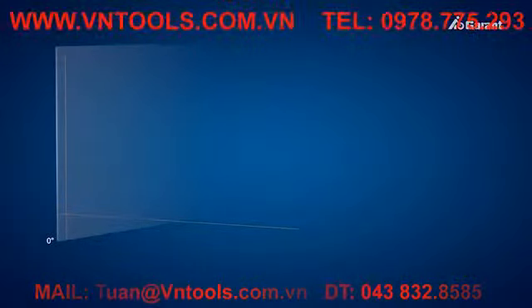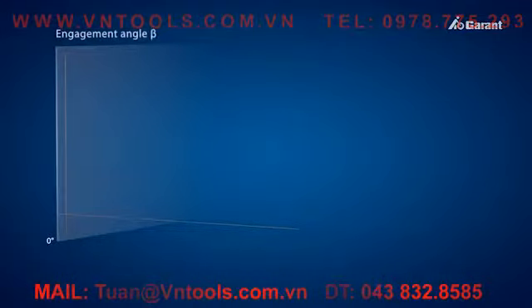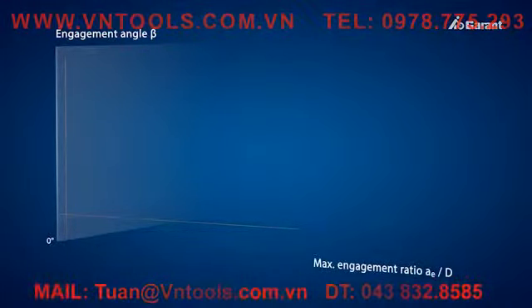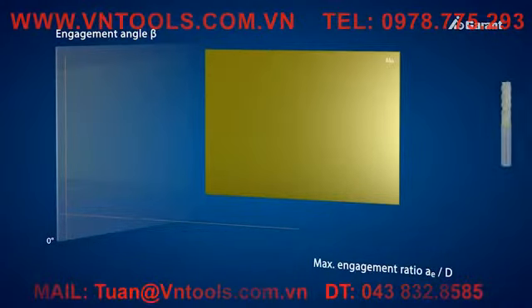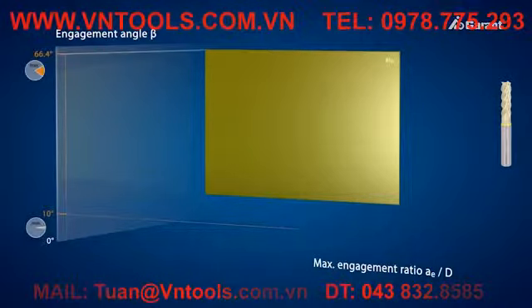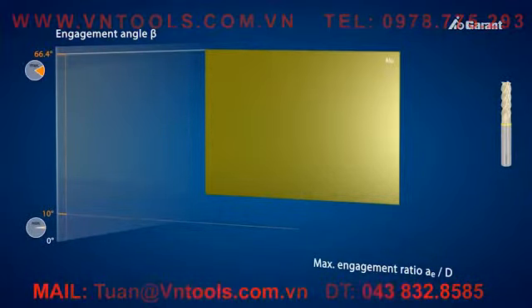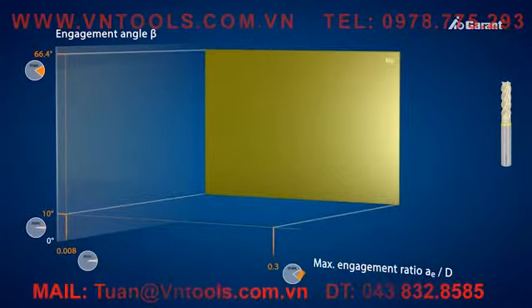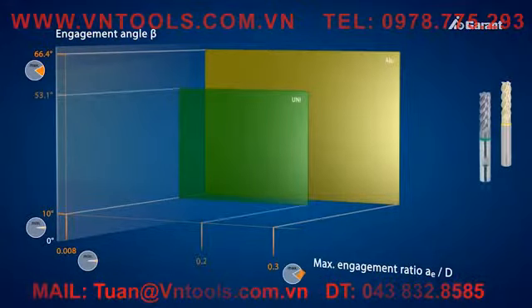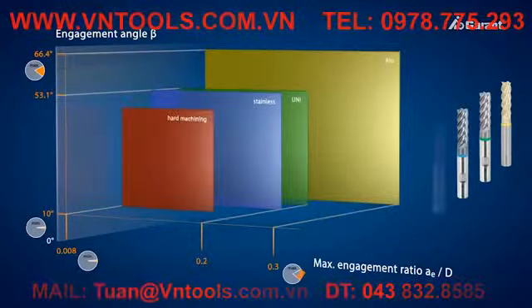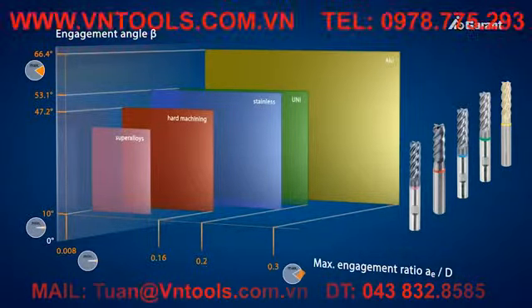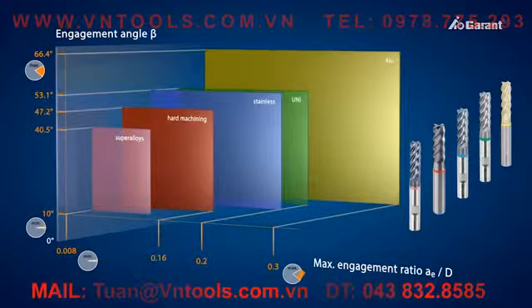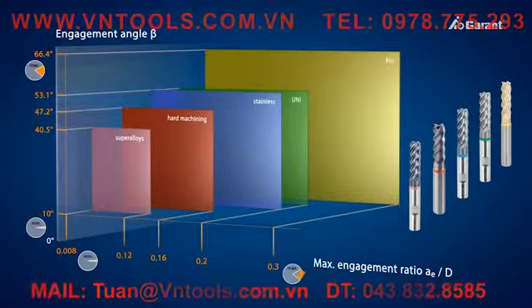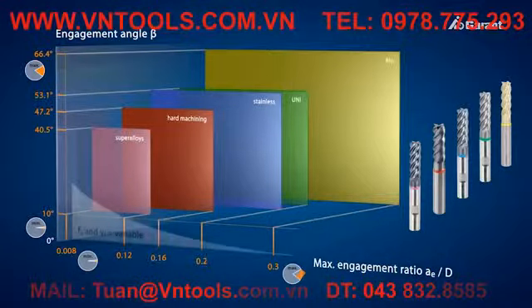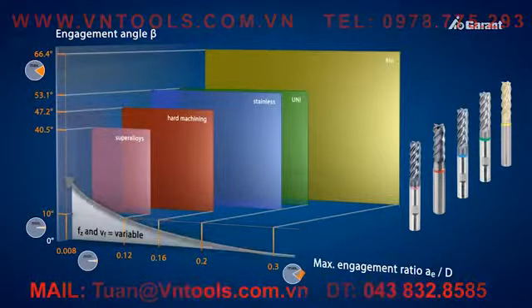Let's consider the optimum application ranges for the tools in relation to the engagement angle beta and the ratio AE to D for the respective material. For machining aluminium, the optimum engagement angle lies between 10 degrees and 66.4 degrees, corresponding to an engagement ratio AE to D of 0.008 to 0.3. Other ranges apply to uni, stainless, hard machining and superalloys, for which the optimum range lies between 10 degrees and 40.5 degrees. That corresponds to an engagement ratio of 0.008 to 0.12. To keep the average chip thickness constant as the engagement ratio becomes less, we have to increase VF.